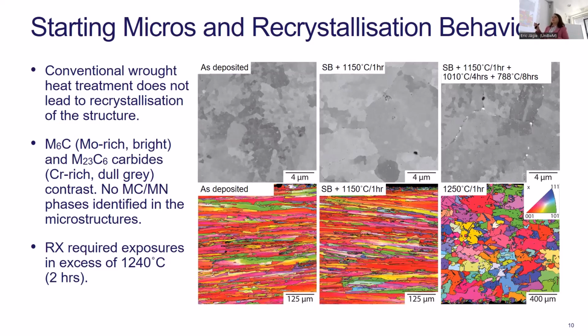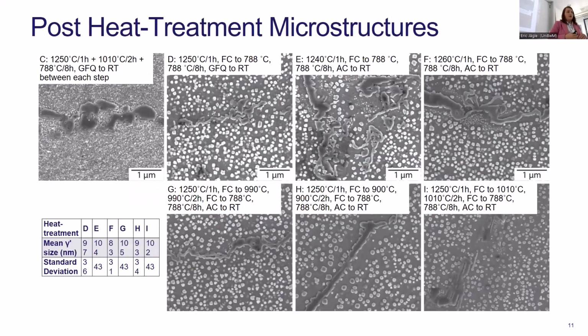The second thing to notice is the recrystallization. So as I said, in the traditional 1150 degrees Celsius homogenization, we don't get recrystallization. So we played around with the temperatures for the recrystallization to see when we would actually induce it, because that was quite an important factor for us. And what we found was that recrystallization needed an hour at 1250 or a couple of hours at 1240. And we looked at different compositions for that, with different durations for that as well. So the main thing was that we were looking at recrystallized material before we were looking at the